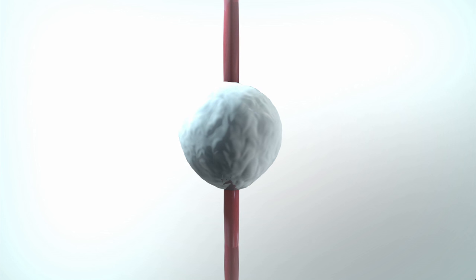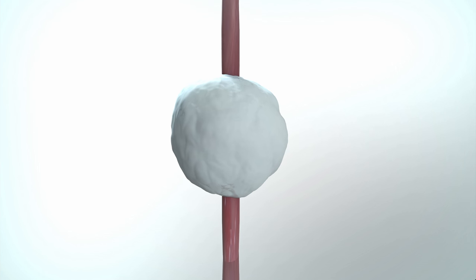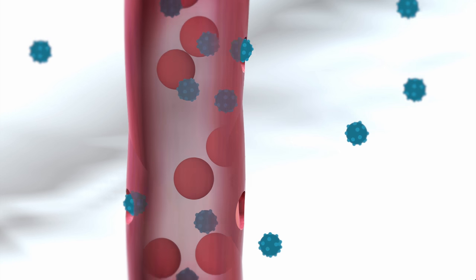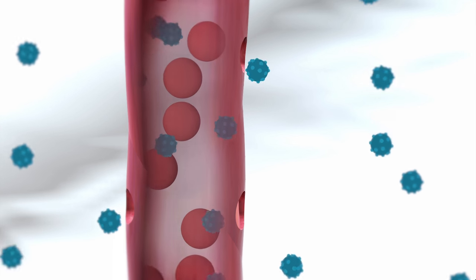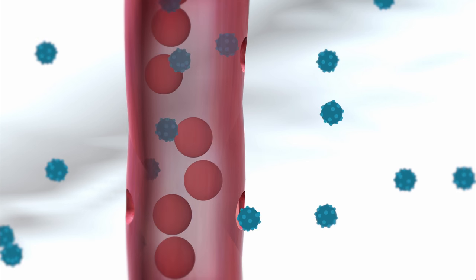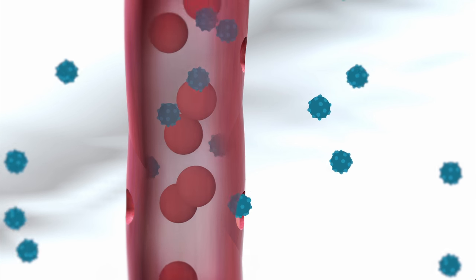Here's a little movie to show you what I mean. This is a blood vessel in the body, and around the blood vessel is a tumor. We inject nanoparticles into the blood vessel and watch how they travel from the bloodstream into the tumor. It turns out that the blood vessels of many tumors are leaky, and whether nanoparticles leak out depends on their size. The smaller blue 100-nanometer nanoparticles can leak out into the tumor, while the larger red 500-nanometer particles stay behind. That means as an engineer, depending on how big or small I make a material, I can change where it goes in your body.